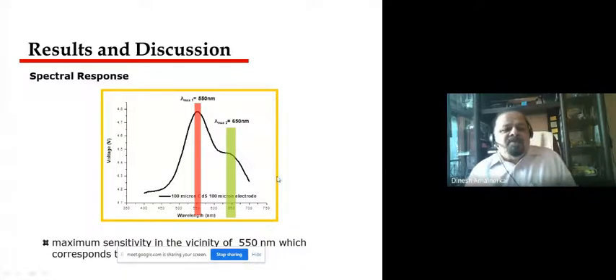Spectral response, as I said, is basically photocurrent versus wavelength of excitation. We get lambda max, the maximum peak, at 550 nanometers, which corresponds to a band gap of say 2.5 electron volts. And we can also see a shoulder here at a wavelength equivalent to say 650 nanometers, which can be due to the impurity excitation, that is the excitation from copper impurity to the conduction band of cadmium sulfide. So this is a typical pattern for doped cadmium sulfide.